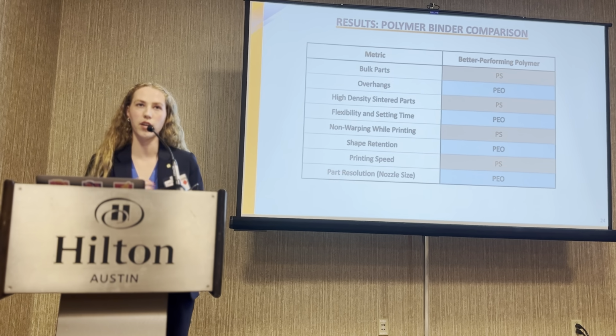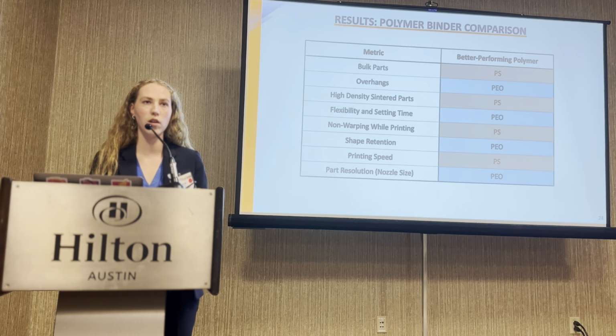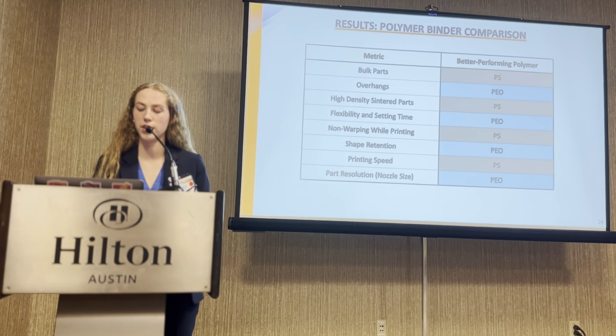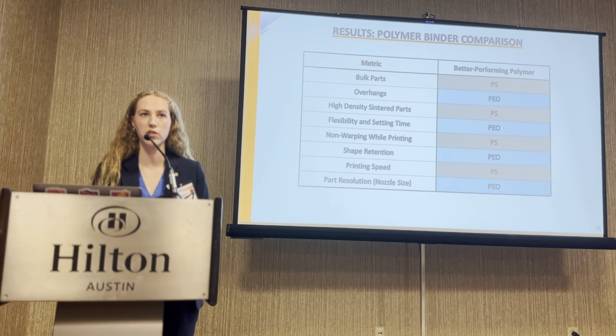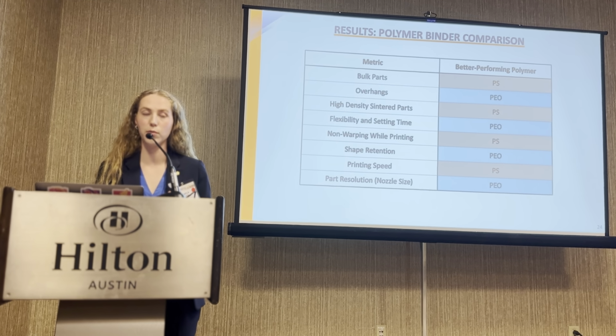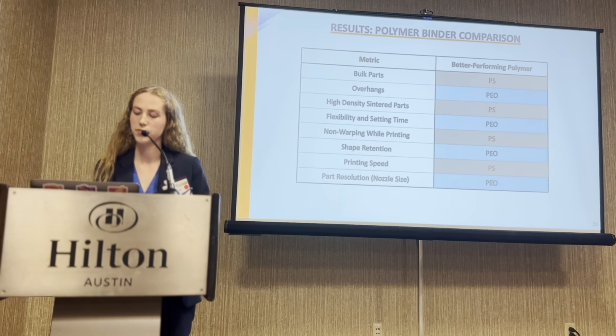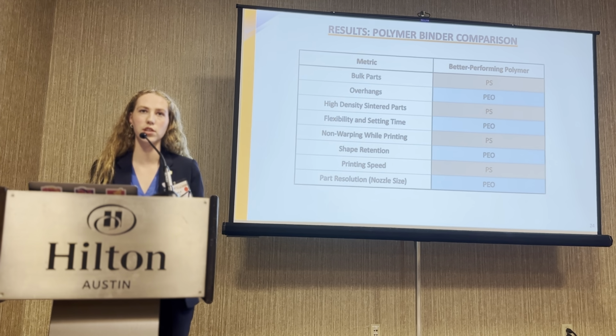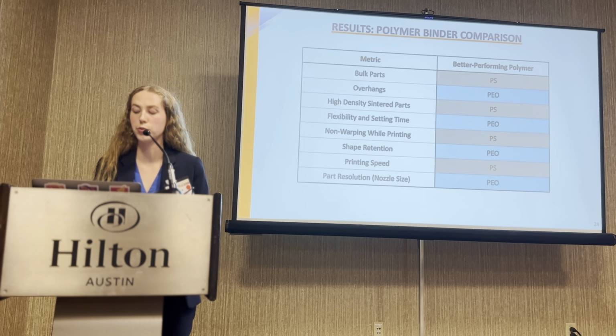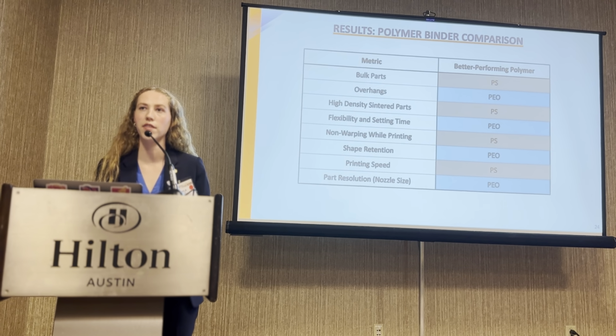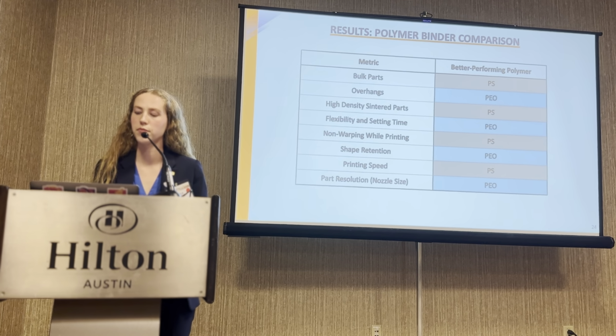PEO burns out into that carbon structure. With more carbon, it supports the shape more during sintering, and PEO has a higher storage modulus, which is better able to create those struts and overhangs. We're experimenting with the addition of PEG to PEO in order to reduce the microstructure and other issues that the polystyrene is stronger in.